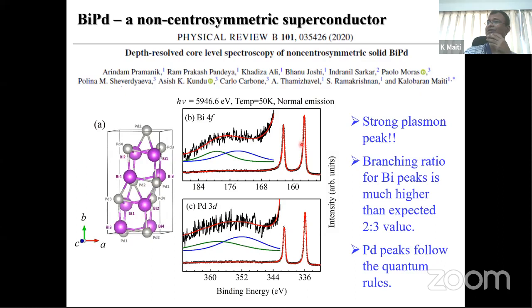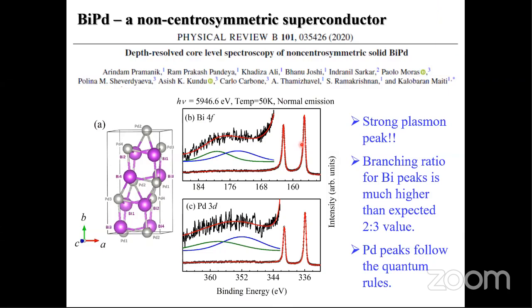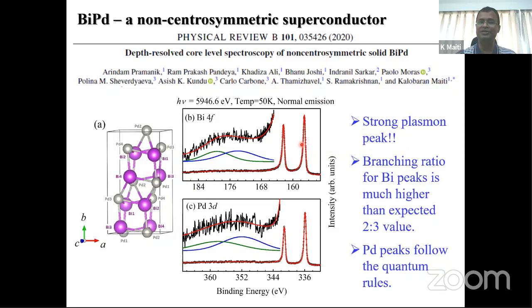We have done a lot of experiments. When you do photoemission, you know that this technique is highly surface sensitive. If you are doing, say, XPS with a typical aluminum K alpha source, where the photon energy is about 1.5 kilo electron volt, the effective probing depth is of the order of, say, 20 to 25 angstrom, which is about 10 layers or so. Now, if you go to hard X-ray, like 6 kilo electron volt or so, then your probing depth becomes much higher, like 40 angstrom. So then we assume that most of the bulk electronic structure can be probed.